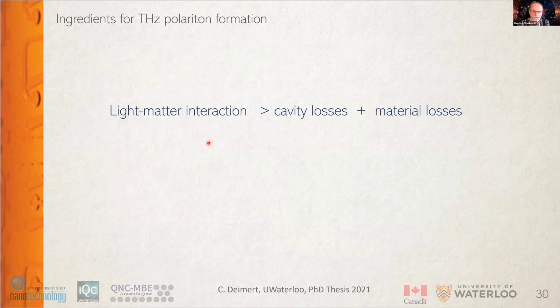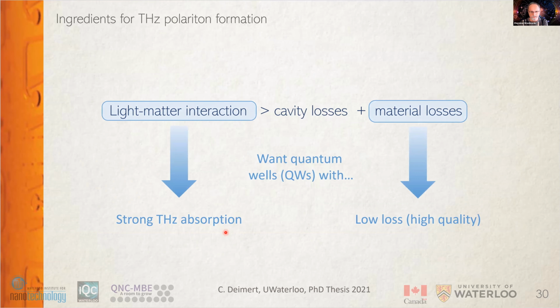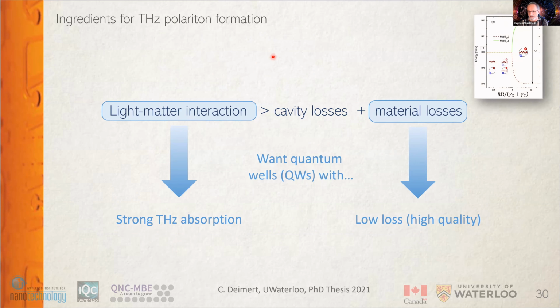We need to get this light matter interaction stronger than cavity losses and material losses. And the only way we can generate the transitions at this energy is in the quantum wells, in the conduction band. So that's what we're doing. We're trying to get possibly stronger absorption and low losses in this system, and hopefully meet the conditions which are necessary to have this strong interaction and formation of those polaritons. So we're trying to generate this splitting into lower and upper polariton, just like I showed in the exciton polaritons.